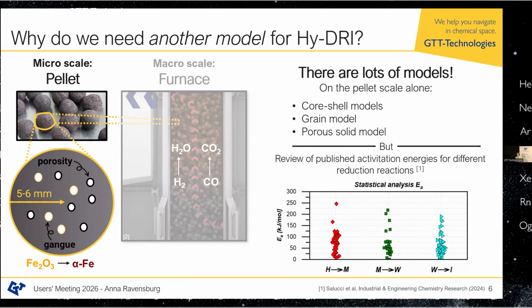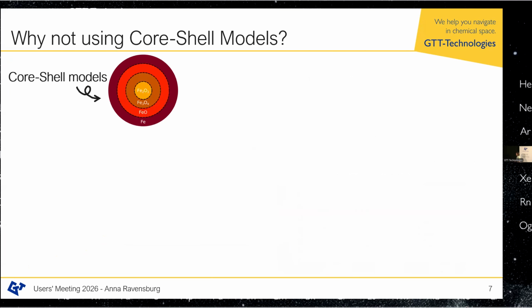And this is also why we have been trying to figure this out. So how can we make these models more accurate, and how can we create a model that considers all of these very different complex processes in order to maybe have a more reliable model that can accurately determine the kinetics of this process? The most famous model is the core shell model. It looks like this. So it's a pellet, and it has distinct regions where one phase is present. So you have the core that is unreacted Fe2O3. Then around this you have a region with Fe3O4, FeO, and Fe. And then these reaction zones move over the course of the reduction.